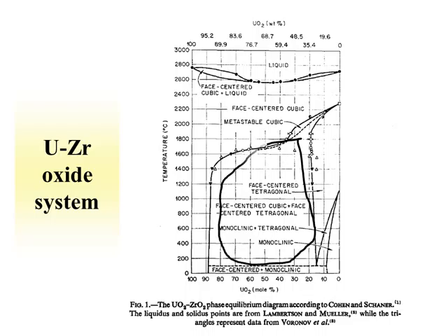Now, in this regime shown here, we have multiple phases formed, face-centered cubic and face-centered tetragonal. So when we started to reach percentages of uranium that were lower than what's shown on the side of this solid solution regime, we start having mixed species. Now this is an example of a system that's important for nuclear fuel, as zirconium is a large fission product. It's also been explored for inert matrix fuels, but this system is also rather complicated, and you can find different data in the literature.